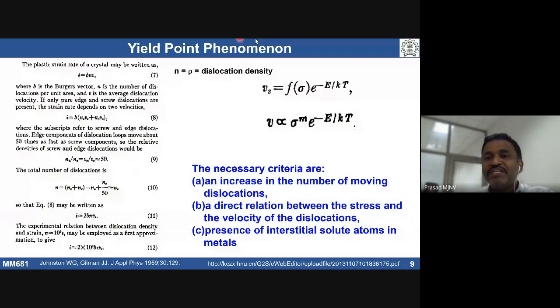So this equation basically tells your velocity of dislocation is proportional to stress. Once it reaches the upper yield stress, that internal strain rate is higher. However, in order to maintain a balance between the internal and external strain rate, this has to come down. But your dislocation density has already increased a lot.